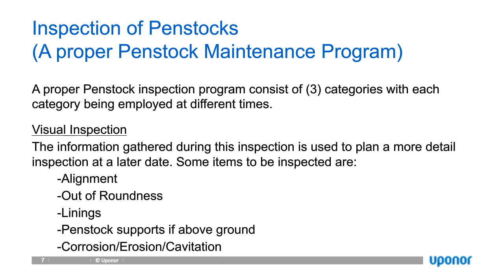But part of the things we're looking at when we're doing the visual inspection is, number one, the alignment of the pipes. Has there been shifts? If it's above ground and it's sitting on concrete girders, do I have movements in that? Particularly if there's soil movements in the soil, or it could be within seismic zones, that's very important. Other aspects, if it's a large diameter pipe, is it out of roundness? Is it now oval rather than being completely round? If you're using concrete or steel, many of them have linings. So part of that is that, do I have perforations or loss of linings in that particular case? And last, corrosion, erosion, or cavitation. I'm going to say erosion.